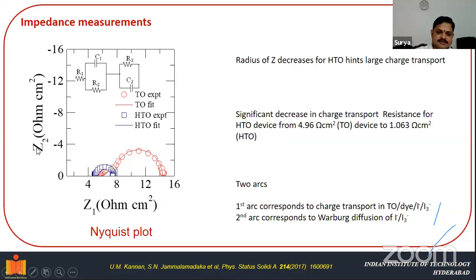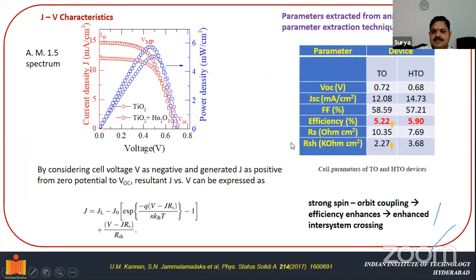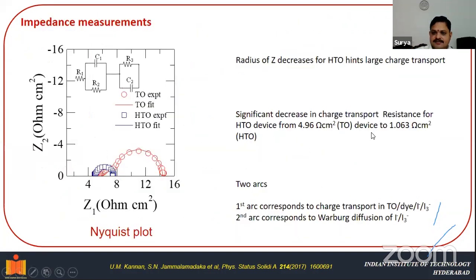If the radius decreases, the impedance decreases. If the impedance decreases, the resistance for the electron flow decreases. If the resistance for the electron flow decreases, that means more and more electrons flow through the device, so the efficiency of the device enhances. You can also understand this from the resistance of the HTO device decreasing from 4.96 to 1.063. Initially the device resistance was 4.96 for parent titanium dioxide, and as soon as we add holmium, the device resistance decreased to 1.063.